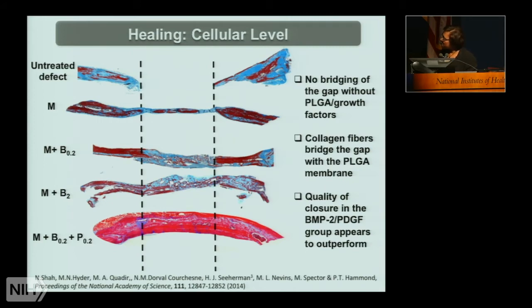And we also are able to, with mechanical measurements, compare them to native bone and see that they match the native bone, unlike what we've generated in the first 2 examples, in which the bone is more brittle and breaks more readily. So we think that what we've done is introduce vascularization earlier in this bone. So this bone is a healthier bone. It's much less likely to become necrotic. But maybe as importantly, we've introduced pathways for a second wave of osteoclasts rather than osteoblasts. And osteoclasts actually remodel bone, and that bone remodeling is what is allowing us to achieve bone which has the mechanical properties that we need.